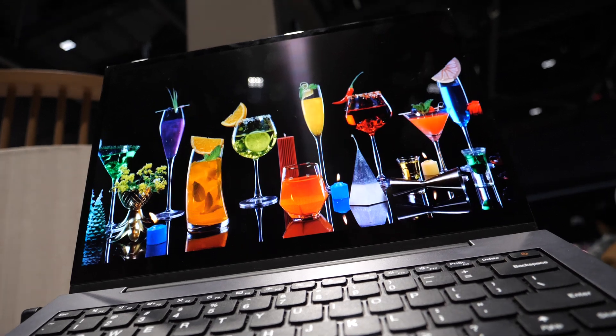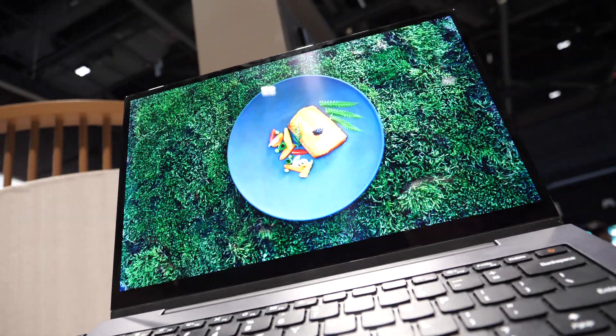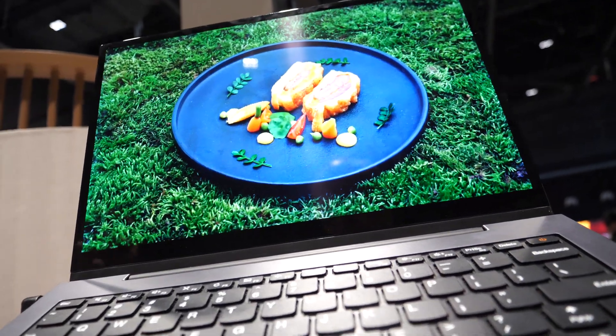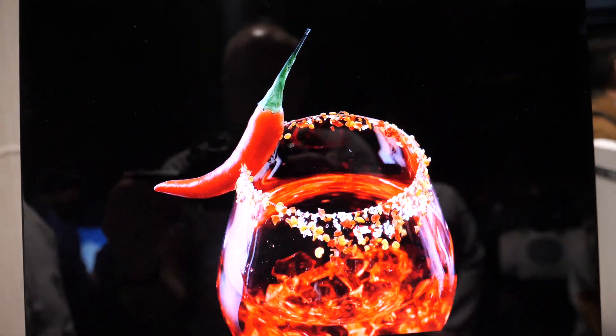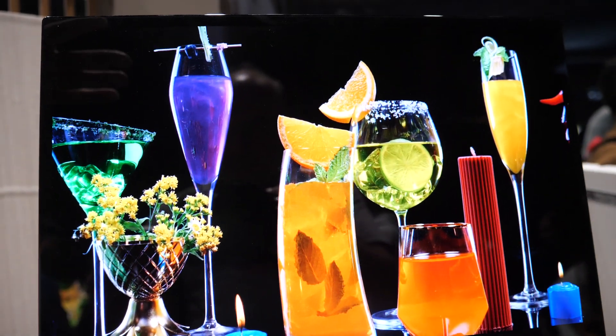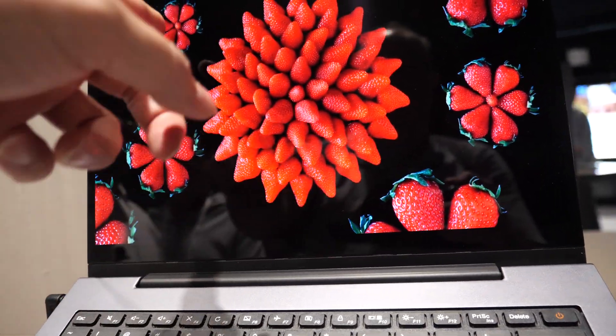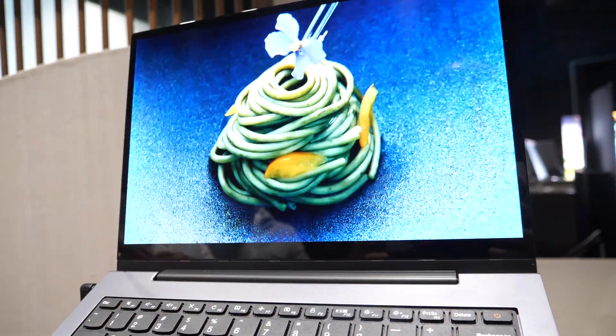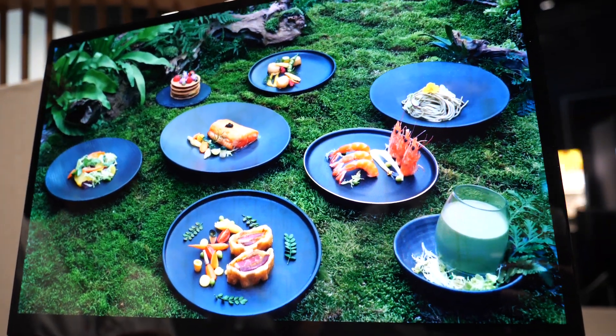What is going to be the lifespan on this kind of device? Is there any risk? There is a risk - it's the blue problem. Right now the red and green already have a similar lifetime as OLED. But for the blue, it's still a problem. It looks nice, but if you keep the screen for, let's say, a month, you can see the blue decays very fast.